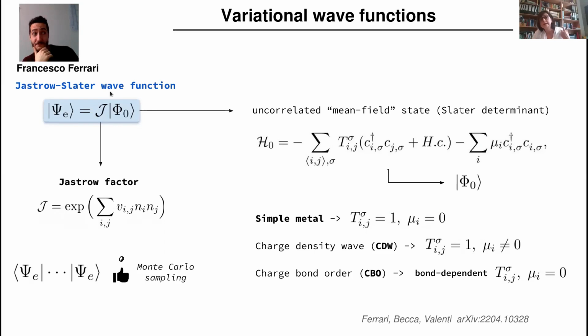In order to include the effect of electronic correlation, even long-range electronic correlations, one includes in the wave function a Jastrow factor, which captures long-range density electronic correlations. The idea is to minimize the energy of this wave function as a function of the parameters from the auxiliary Hamiltonian and from the Jastrow factor. With this type of wave function, one can, in principle, obtain the various phases in the phase diagram of this extended Hubbard model, depending on which parameters minimize the energy.